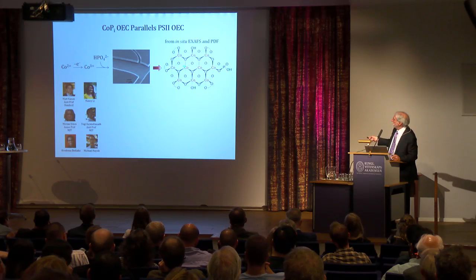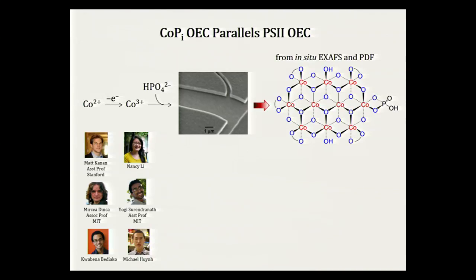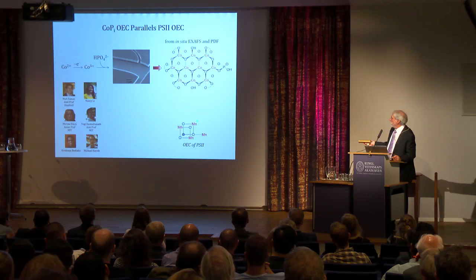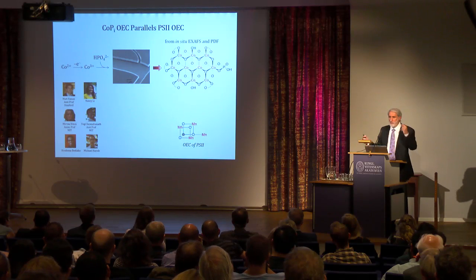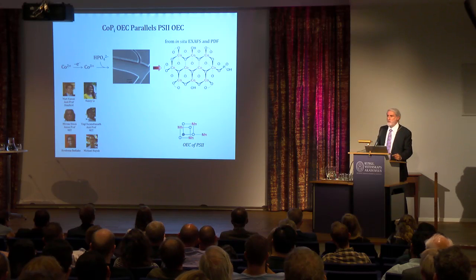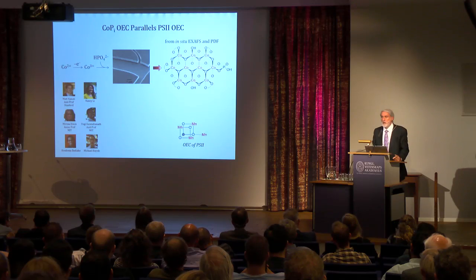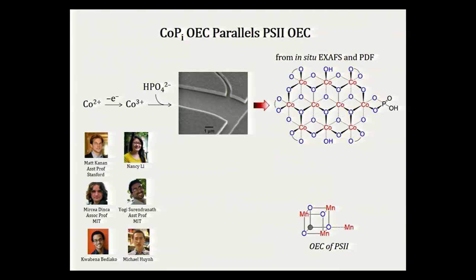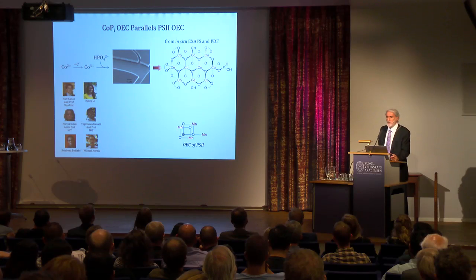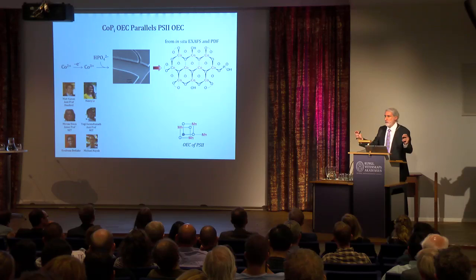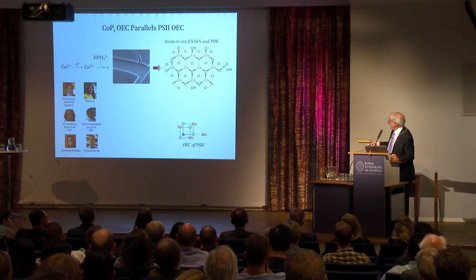And the structure is this. The cobalt gets stitched together with oxygens, and it makes this cluster of cobalt atoms. Now, what's interesting about this cluster is this is the cofactor, the simplified line drawing of the cofactor of photosystem 2, the one that does water splitting. It's called the oxygen evolving complex with manganese. And that is a cubane, so it's a cube of manganese and oxygens, and then this manganese has a famous name in the literature. It's called the dangler, because of a man named David Britt.